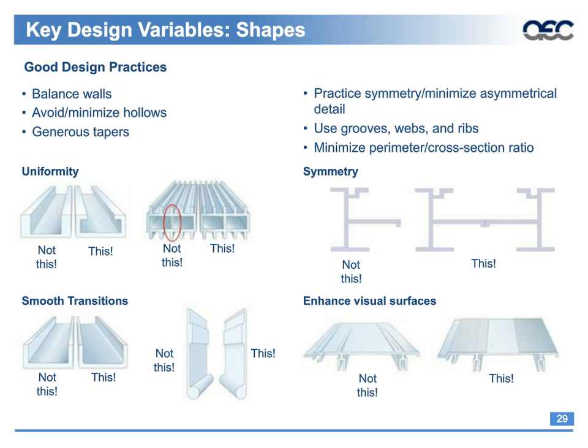Smooth transitions are better than having very sharp corners. So if you look in the lower left of the graphic, you'll see that there are very sharp corners. Those are possible to extrude, but again, they limit the extrusion speed, whereas the smoother shapes work better, similarly on the shape next to it. In the upper right, symmetry: it's good to have symmetrical shapes, but it's certainly not required. In fact, most shapes are not. But often, if you can make a shape symmetrical, you're better off.